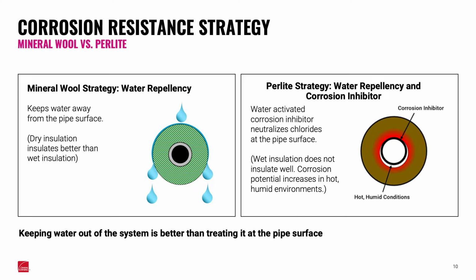What the Perlite product does in addition to water repellency is that it has a corrosion inhibitor in it, so that if any water does happen to leach through the insulation, that water is removed of all corrosive materials, typically chlorides, before it reaches the pipe surface, which is good, except the problem is now we have wet insulation. And again, that inner core where it's red, that might have that hydrophobic agent burn off. So now we're going to have something there that actually absorbs water.